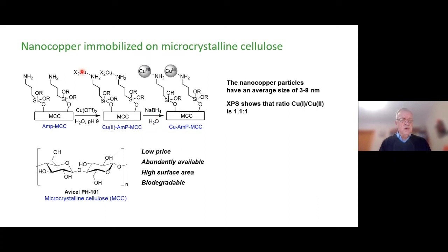Now we bind copper 2 as we've done before with palladium 2, and then we reduce with sodium borohydride. But in this case, you get a mixture between copper 1 and copper 2. And that is the nanocopper catalyst, and the particle size is about 3 to 8 nanometers, and the ratio between copper 1 and copper 2 is 1.1 to 1.